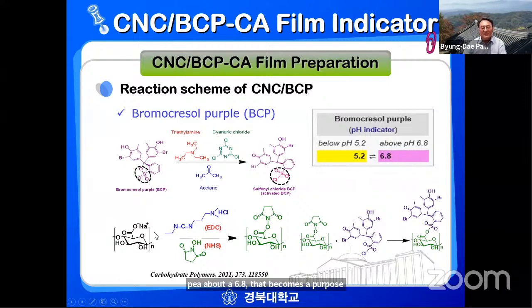So we have this APS oxidation, which also provides a carboxyl group; you add sodium hydroxide here, and then you get the sodium carboxylate group. And then we use EDC and NHS, the same as the previous bromocresol green, added the byproduct, and then we make a reaction with the activated bromocresol purple, and then we made the bromocresol-conjugated CNC like this.